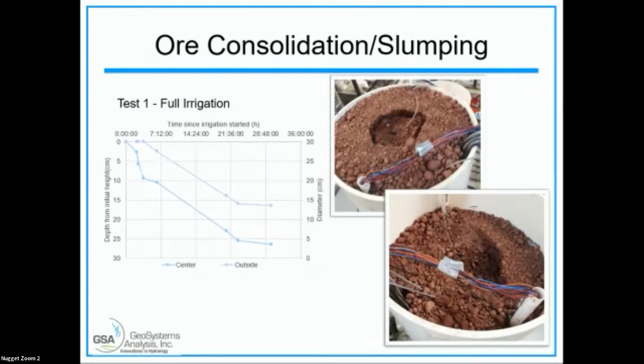Okay, so this is what we're looking at here. This is a picture of the column, very shortly after the irrigation was started, with the full irrigation test. We start to see a collapse zone. And then by the time the test ended, the ore had collapsed quite a bit throughout the column. On this graph, this is time and this is the depth of collapse. This line right here is what's happening in the center, and this is what's happening on the side. The collapse here was close to 20% in the center. We had over 25 centimeters of collapse in the middle and around 15 centimeters of collapse along the sides, along the bank. Next slide.